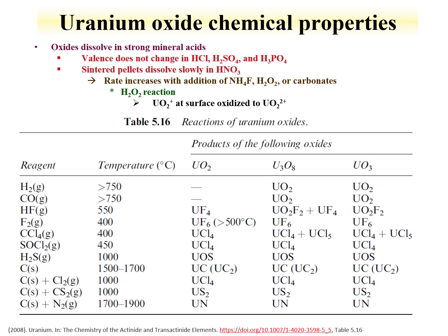And here's an overview of some high-temperature reactions that some of you may be doing in the laboratory, where we have different starting products, oxides, and a reagent, and what can be formed from these reactions. For instance, there's a project going on where we're trying to look at the formation of uranium tetrachloride, and we're using other routes, but one could use, for instance, carbon tetrachloride at 400 degrees with UO2 to form uranium tetrachloride. And as we see, if we use U3O8, we get a mixed species, and the same with UO3.